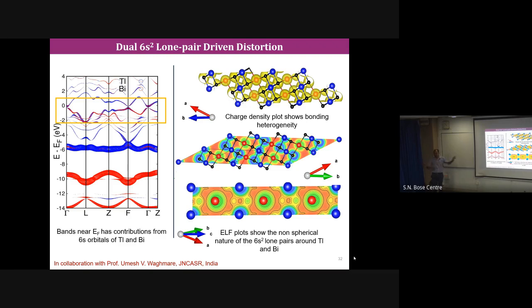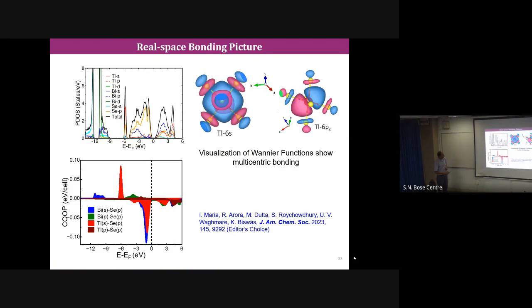Okay, so I'll show you the MO diagram that we have drawn, and from the ELF plots or charge density plots, the bismuth selenium is a very nice covalent bond, whereas thallium has gone more towards ionic but not fully ionic. So that understanding we have from this plot, and then in collaboration with Umesh, we have calculated the partial density of states, and you can see the valence band is constructed by the selenium p orbitals, and this small blue and red one is coming from the s orbital of thallium and bismuth. So they actually mix in the valence band.